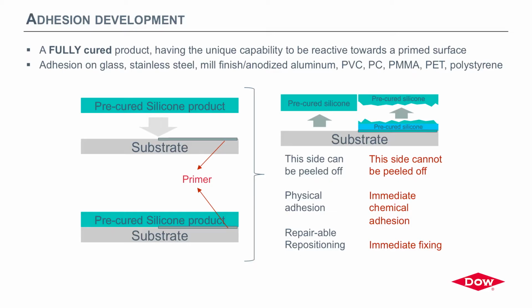We can play around with the formulation. We can achieve a variety of hardness that goes from very soft gels to soft elastomers. But what is really unique about this technology is that it is able to develop post-cure adhesion on substrates. So if you take a piece of conventional structural silicone, like our 993, for example, you make it cure on Teflon, you take it off, you will never, after cure, make it stick again to any kind of substrate. So this technology can do that, and in a quite easy way.